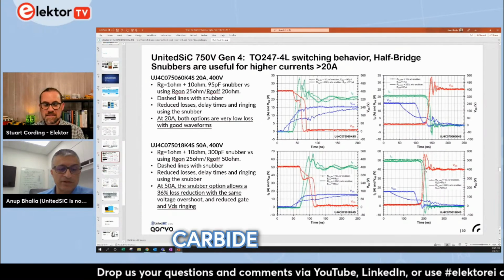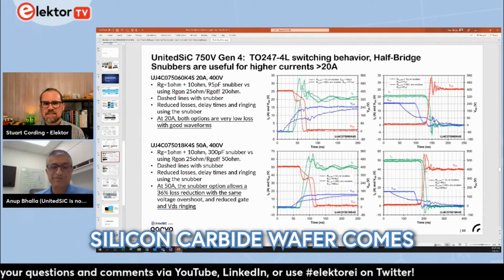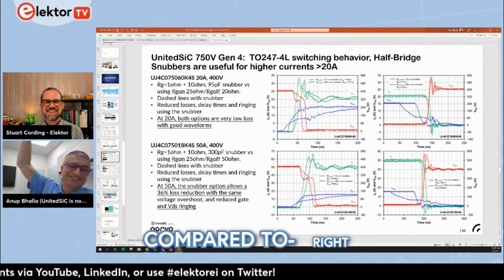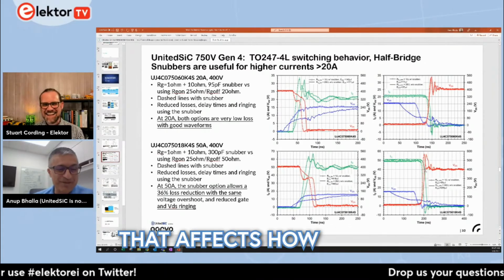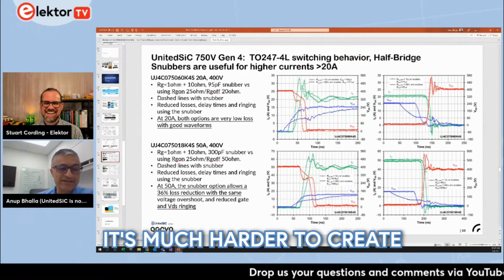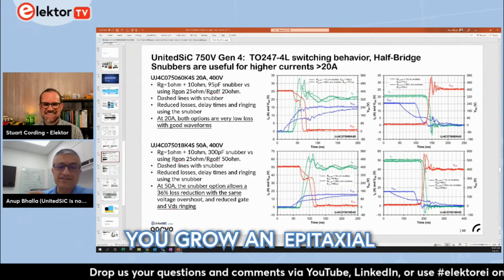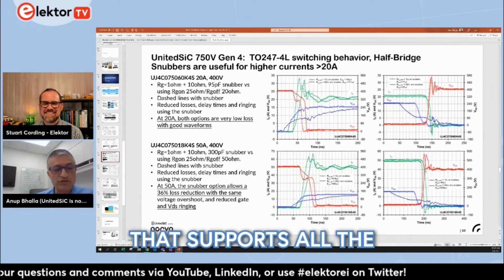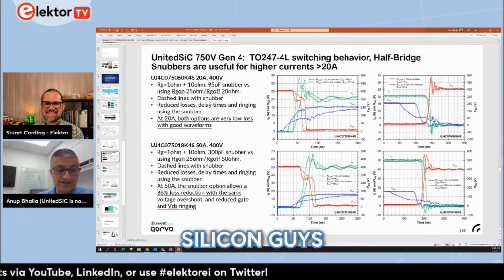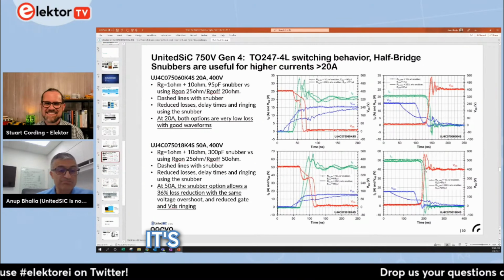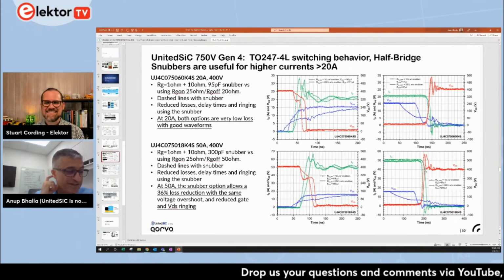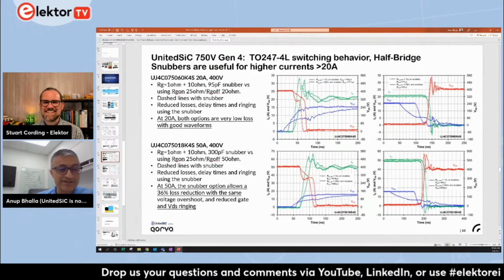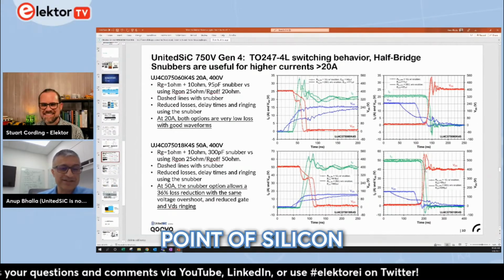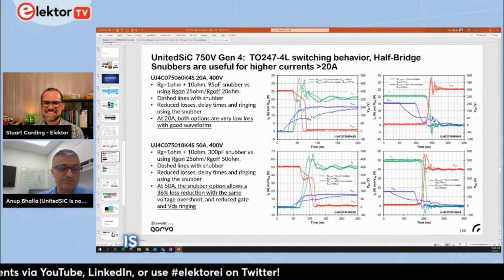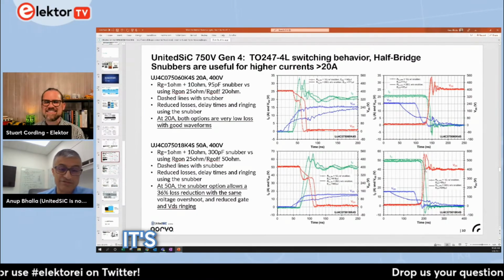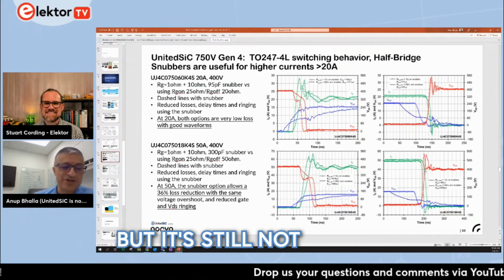There's a lot of similarities. You start with a single crystal silicon carbide wafer. It's just that the silicon carbide wafer comes from a boule which is just this big compared to a silicon one that is enormous. So that affects how much the starting material costs. It's much harder to create. And then it follows the same process. You grow an epitaxial layer on it, which is the layer that supports all the voltage in a vertical current carrying device. We did that in silicon, and we do that in silicon carbide. It's much harder in silicon carbide because instead of at 1000 C, you've got to do it at 1550 or 1600 degrees Celsius. That's about the melting point of silicon. And then it's grown with a lot more defects, and the material is much more imperfect compared to silicon. It's very good now, and it's evolved a lot, but it's still not silicon.